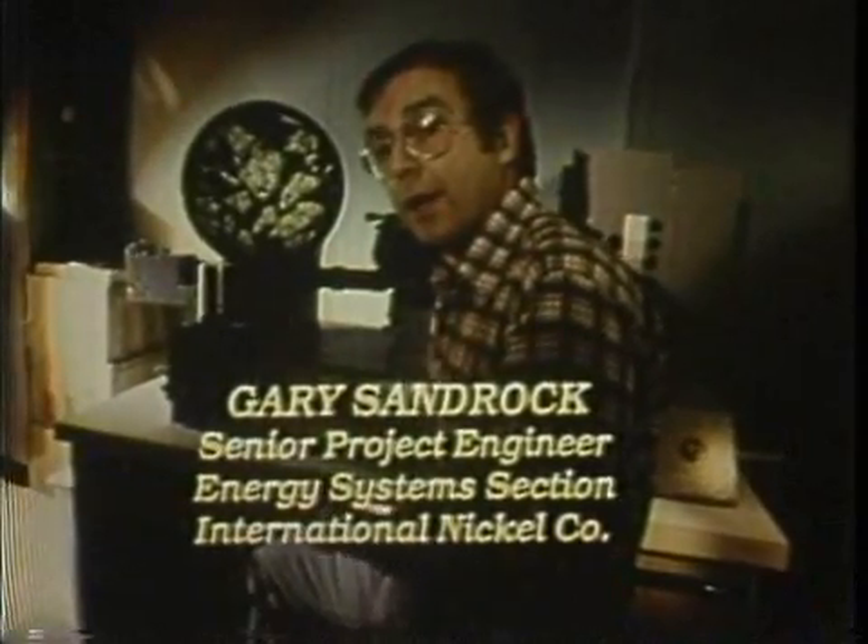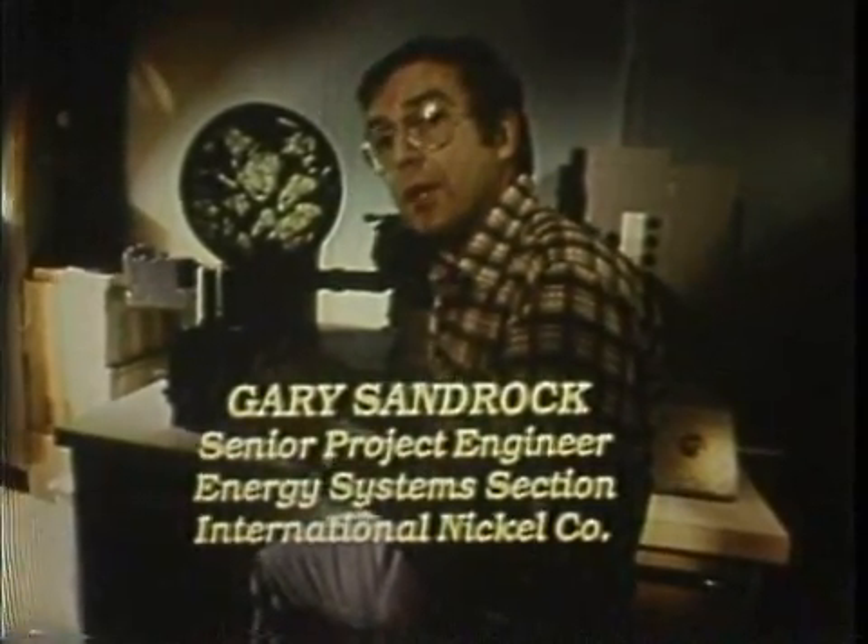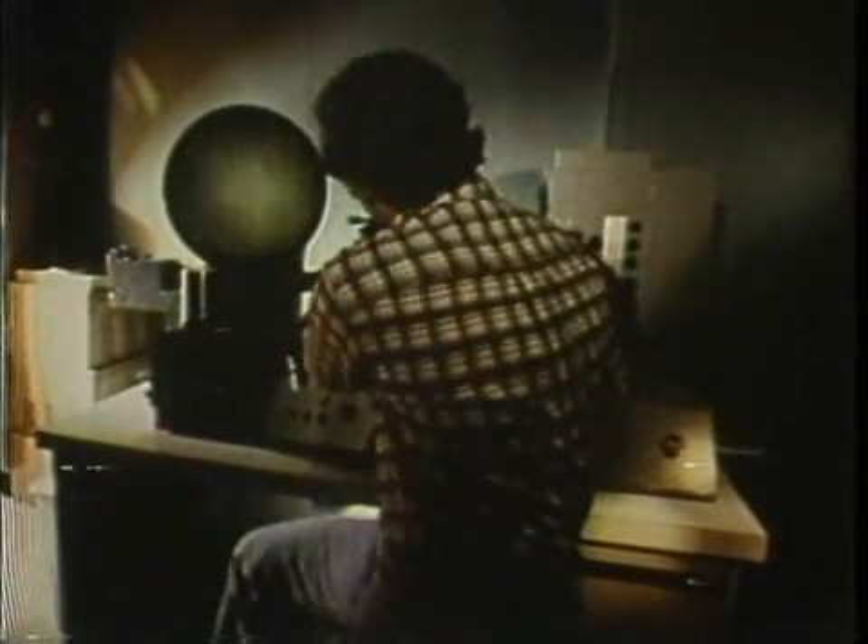What we have are some iron-titanium particles here under the microscope. Each particle is about the size of a grain of sand. What this shows very nicely under the microscope is that iron-titanium and all the hydrides are really very similar to water sponges for water — they're really solid sponges for hydrogen. You can see it looks very much like a sponge in cross-section. It's full of cracks and porosity, and just like a water sponge soaks up water, these hydrides — iron-titanium in this example — soak up hydrogen through these cracks.